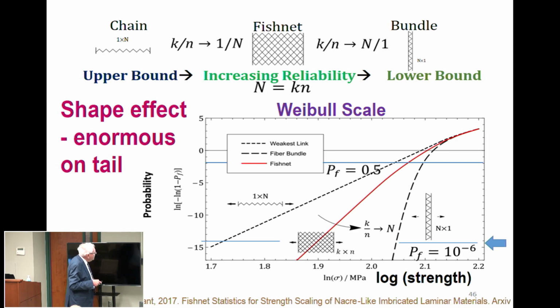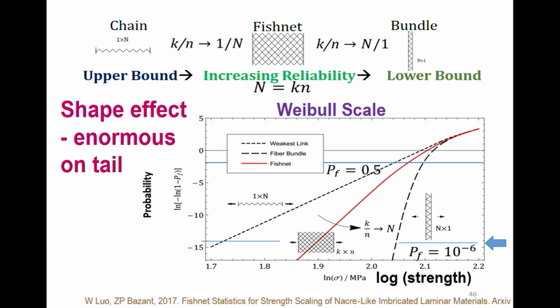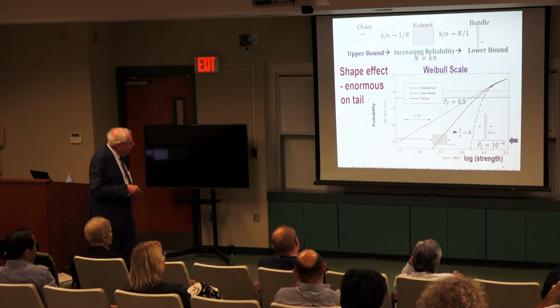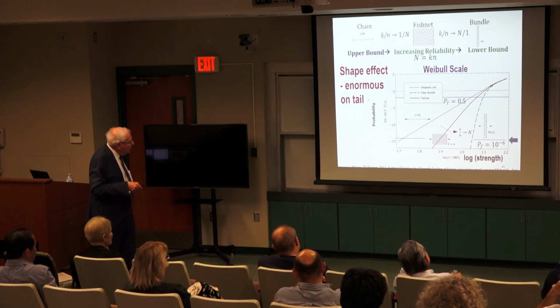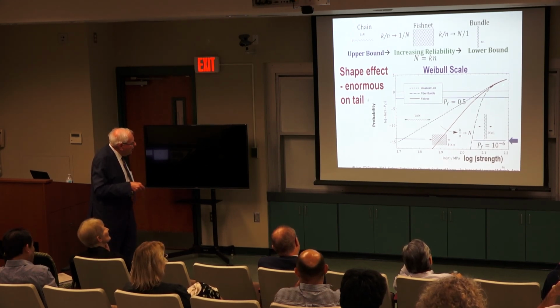Two rigid plates and fibers in between. The opposite, if you extend it longitudinally, you get a chain. So fishnet statistics provides a continuous distribution from Weibull to Gaussian distribution. That's shown here schematically. If you change from a chain to a bundle, how the distribution changes in Weibull scale. This is Weibull distribution, and this is Gaussian distribution in the same scale.